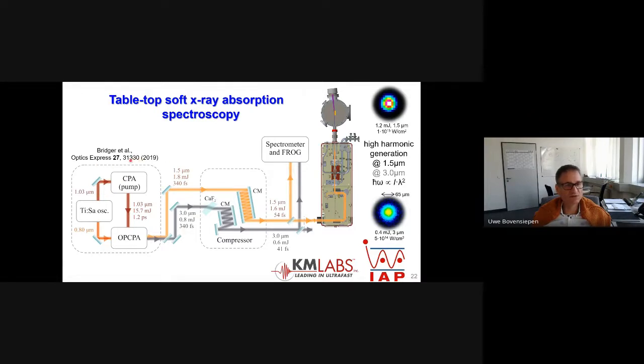We can read on this laser in this publication. It's pretty sophisticated, so we have a large bandwidth emission of a titanium sapphire oscillator, which synchronizes the OPCPA as well as the power amplifier of our pump. And then we get emission at 3 micrometer as well as 1.5 micrometer. Using chirped mirrors, we compress this light in combination with dielectrics. And we get then here at 3 micrometer, 41 femtosecond at several tenths of a millijoule emission. So this is 0.6 millijoule. And at 1.5 micrometer, we even get 1.6 millijoule, just a bit more than 50 femtoseconds.